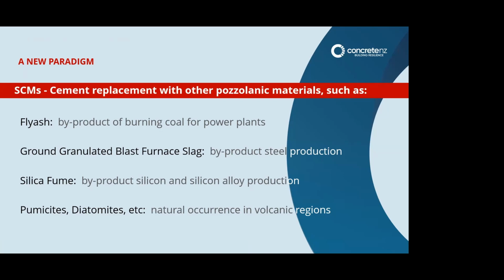Industry byproducts are, for example, fly ash, which is a remainder from burning coal, sitting at the top of the chimney at power plants. And here we have a replacement of about 30-35% of cement. Our 3101 at the moment allows for 30% replacement. Slag from steel production is much more potent. Slag can easily replace cement up to 90%. However, our standard at the moment says 65% would be the maximum. So everything else would be an engineered mix, a kind of alternative solution. However, it has been done in New Zealand. I'll talk about that in a minute.